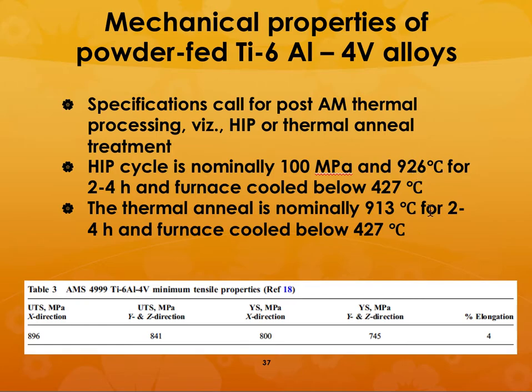For example, if you are going to be doing hipping, you are normally going to do that at 100 megapascals at 926 degrees centigrade. Why do you do hipping? Hipping, so that if there are any kind of defects on the subsurface, they will all get completely removed.